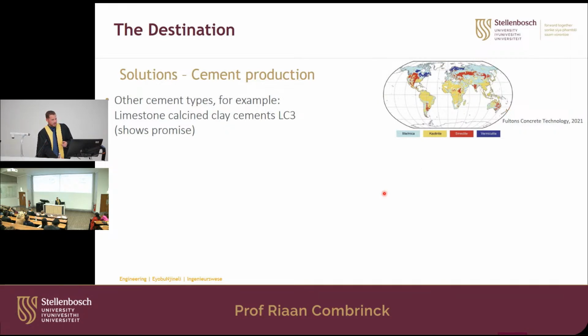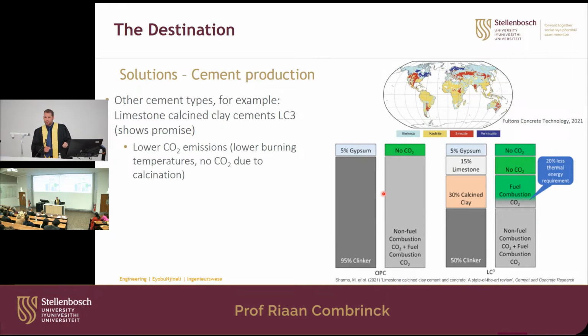So if you take this clay, you don't have to heat it up to 1,400 degrees, only about 600 to 800 degrees, so less CO2 is given off due to the burning of fossil fuels, and also there's no CO2 given off due to the calcining process. So if you just add 15% limestone and 30% calcined clay with this new type of binder, you can almost halve the amount of CO2 that is produced compared to a normal OPC mix.